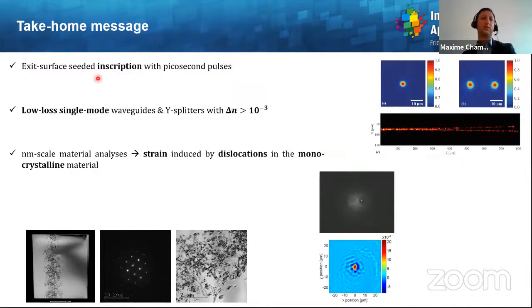We have demonstrated the exit surface seeded inscription of waveguides with picosecond pulses. The waveguides are low loss and the refractive index change is higher than 10 to the minus 3. And the nanometer scale analysis allowed us to claim that some strain was induced by the dislocations provoked by the laser pulses in the monocrystalline material.